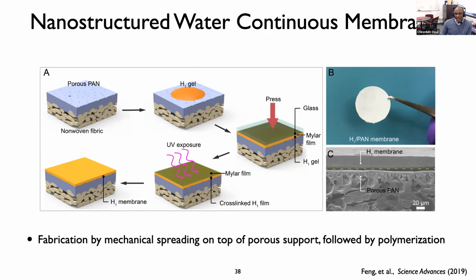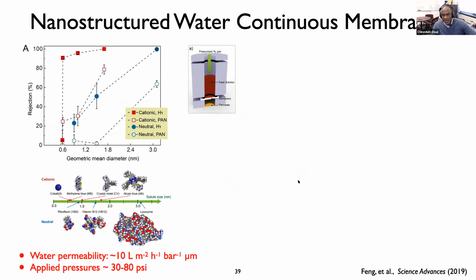So our first foray into the membrane space involved the creation of membranes by physical pressing. So we took these highly ordered gels and we pressed them down to thicknesses of about 20 or 30 microns. And we formed composite membranes by supporting these gels on porous polyacrylonitrile support layers. And the membranes that we created in this fashion, we tested in dead-end filtration with a variety of cationic and neutral dyes, and saw that we had interesting cutoff behavior at about 1 nanometer.